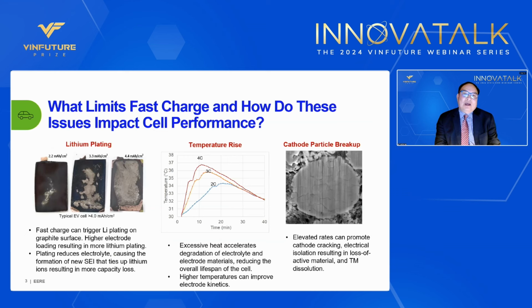Now, you may ask yourself what limits fast charge and how do these issues impact cell performance? On the left-hand side, one of the reasons is lithium plating. You can see that as the loading increases from 2.2 to 3.3 to 4.4 milliamp hour per centimeter square. In other words, when you build an electrode thicker and thicker, you get more lithium plating. As more lithium plates, it reduces electrolyte, causing the formation of new SEI that will tie up lithium ions, and eventually you have more capacity loss.